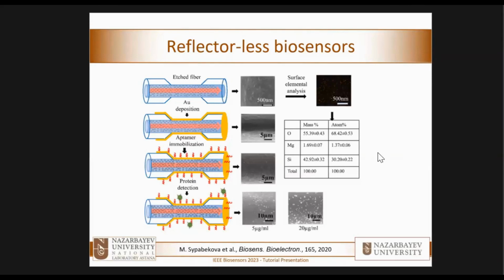What we actually used here is a fiber that has the core doped with nanoparticles. It seems that the fabrication is quite complicated, but in reality that is entirely done in the preform of the fiber. When the fiber is drawn, it forms several defects in the core at the drawing point. But after the fiber is drawn, it looks like a standard fiber. So you can splice it and use it like a standard fiber. You can fabricate hundreds of meters, and that works. So now we have a high scattering content, and we can tolerate these losses.